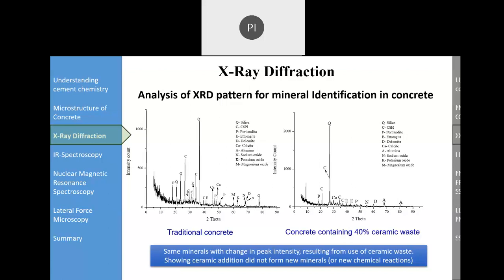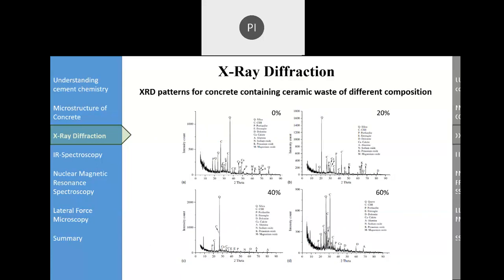So in traditional concrete, we got in the end silica, CSH, portlandite, ettringite, etc. And in the concrete containing 40% ceramic waste, more or less we got the same minerals. Why it is important is that overall it has no major effect on the mineralogical composition of the concrete if we are using ceramic waste. So that means we don't expect any major change, any adverse effect on this concrete when we are using ceramic waste.